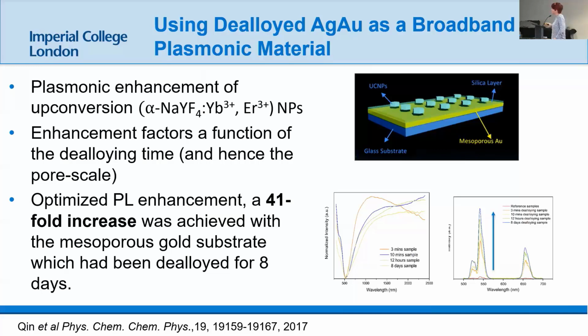And so what we've done here is coupled, these are upconversion nanoparticles, and we use those in solar devices to convert solar radiation that's coming in at the infrared region up to an energy where we can then use it in a sensitized device, right? So it allows us to basically shift the wavelength of incoming radiation to use it more effectively. And when you couple this optically active material to something that's got an active plasmon, you can get enhancement of the electromagnetic field very locally.